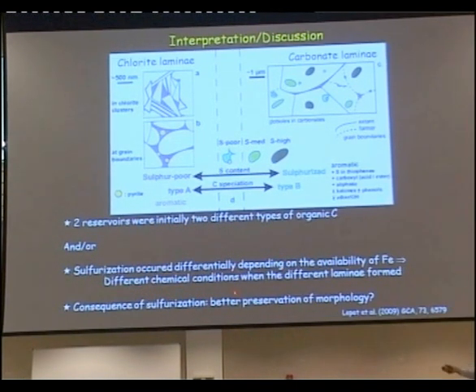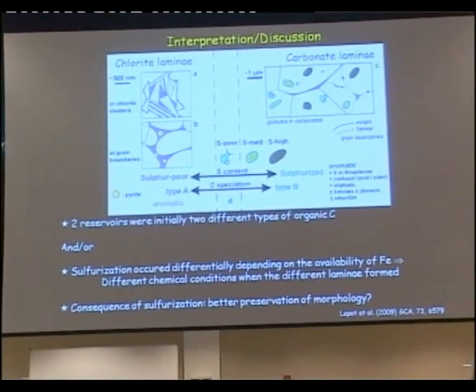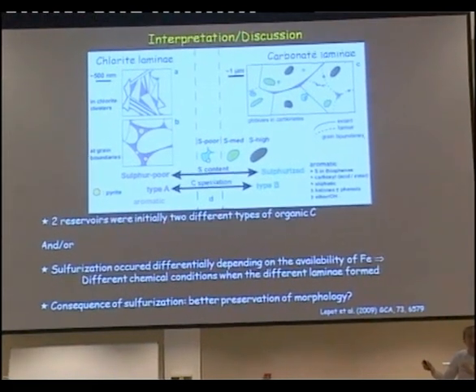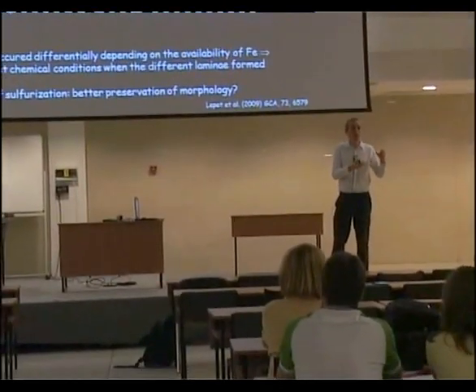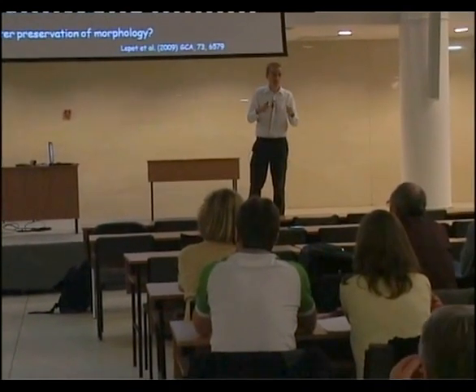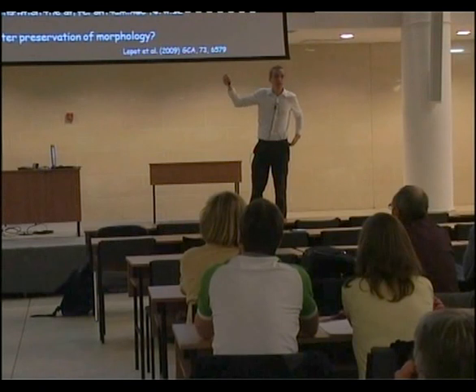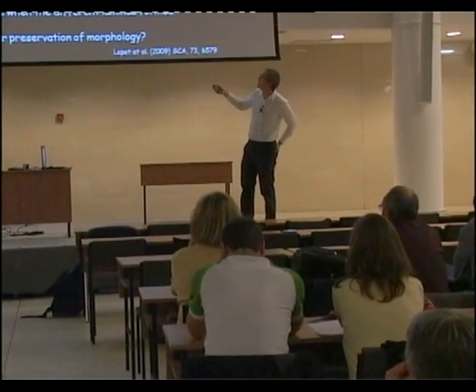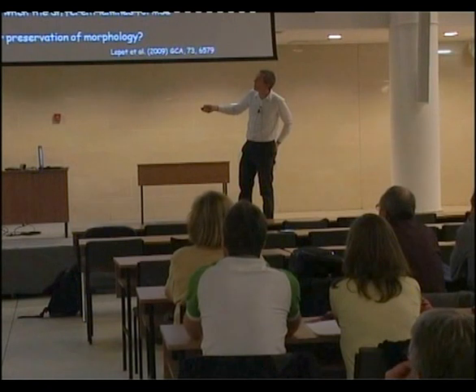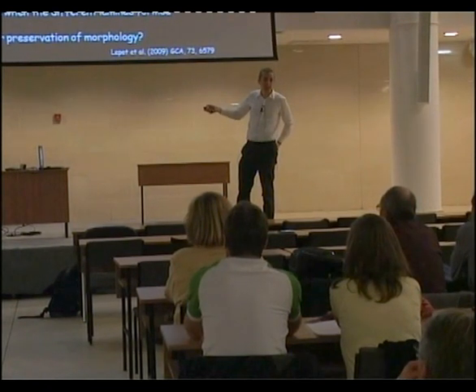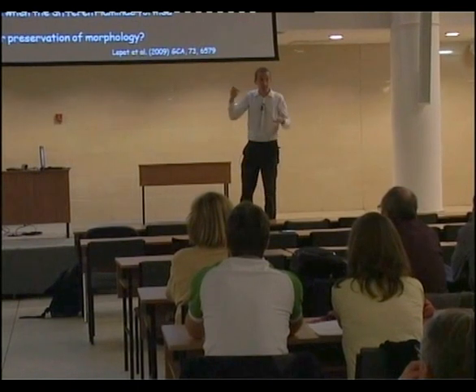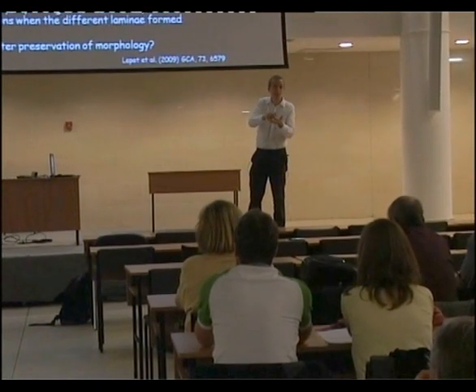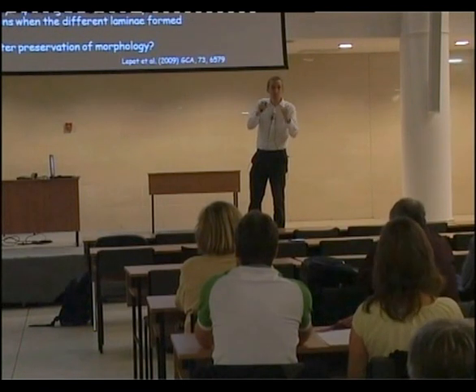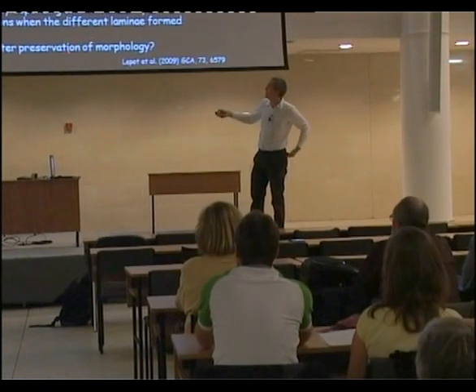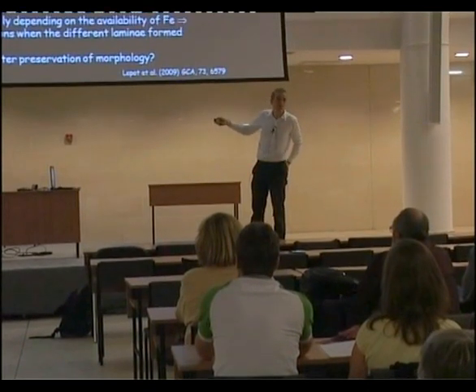A second possibility is that some of the carbon was easier to sulfurize than the other one. So sulfurization occurred after the formation of the stromatolites. The carbon that was within the carbonate was easy to sulfurize. The carbon that was in the chlorite was not easy to sulfurize, and that would explain things. Anyhow, what we know is that sulfurization, this has been shown by organic geochemists, when you add sulfur species to the organic carbon, you start protecting the organic carbon from further degradation. And so you might end up with better preservation of morphology.